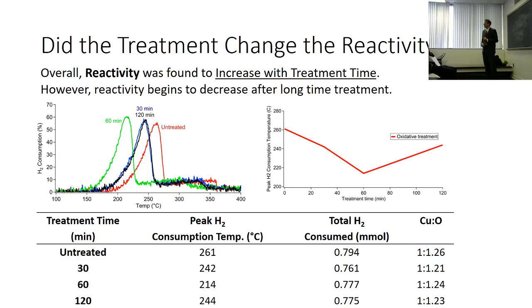Second piece of information you can get from this is if you look at the area under these curves and integrate them, you can get how much hydrogen was consumed, total. And that should be equal to the amount of oxygen that was in your material.